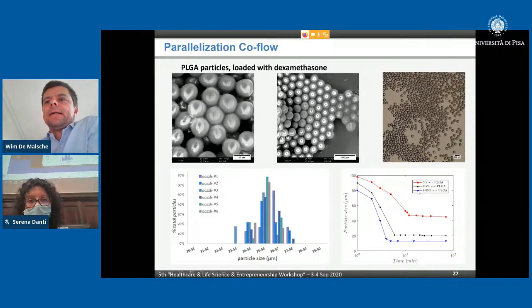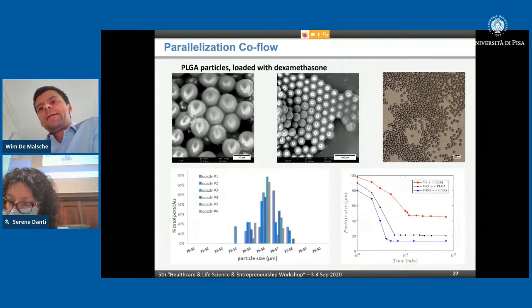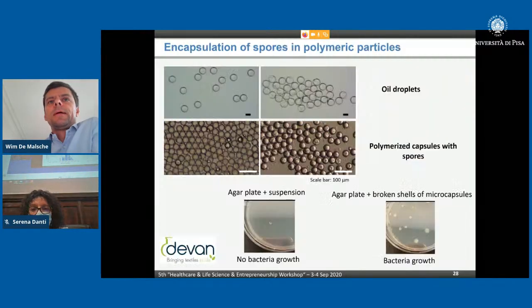I also want to add that depending on the concentration of the PLGA that we use, if you use lower amounts of PLGA, during the formation of the particle, the liquid is extracted by an anti-solvent extraction, and so the less concentration of PLGA, the more the particle shrinks. You can see that even starting from droplets of 80 or 100 micron, we can go down to 10 to 20 micron particles just by playing with the concentration. So there's quite some flexibility there, and that's another parameter we can optimize.